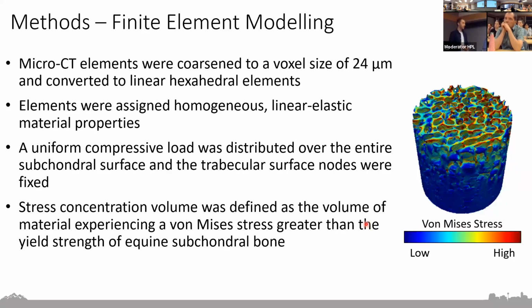And finally, we developed some micro CT based finite element models. So our elements from our micro CT images were coarsened to a voxel size of 24 microns and converted to linear hexahedral elements. And we did a mesh convergence to make sure it was sufficiently converged at this element size. We then assigned homogeneous linear elastic material properties, and a uniform compressive load was distributed over the entire subchondral surface with the trabecular surface nodes fixed.